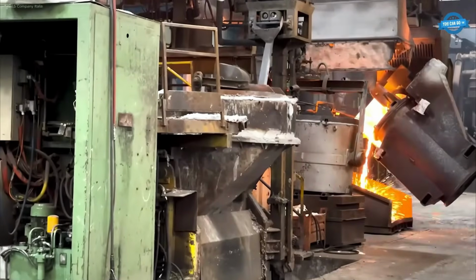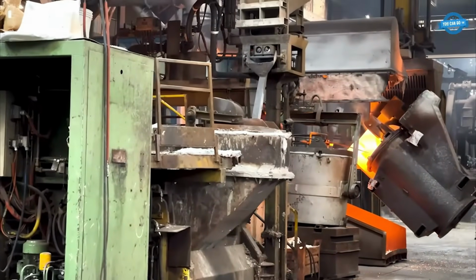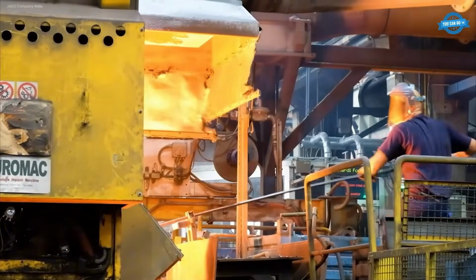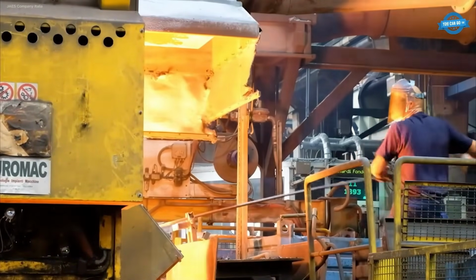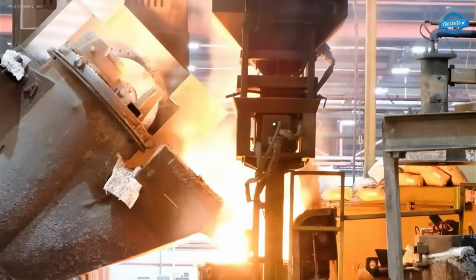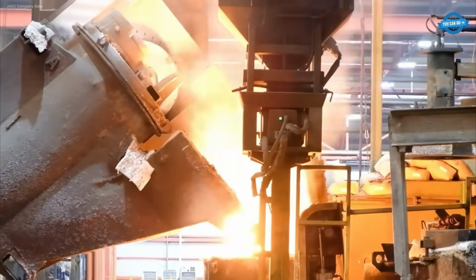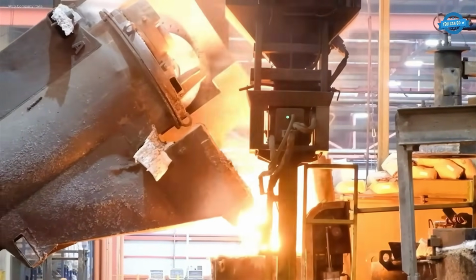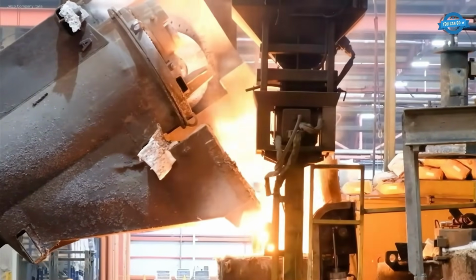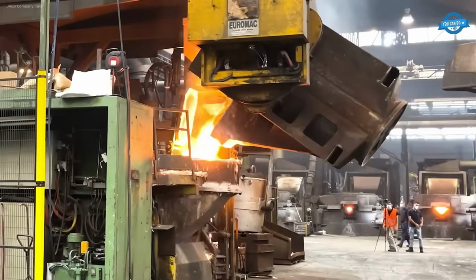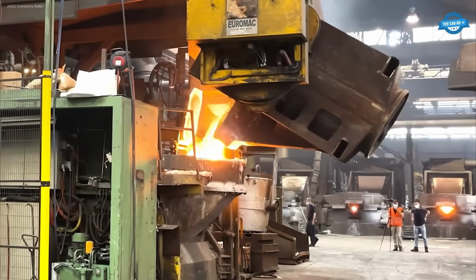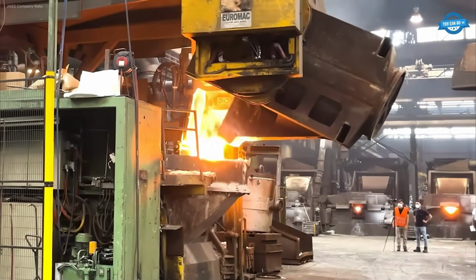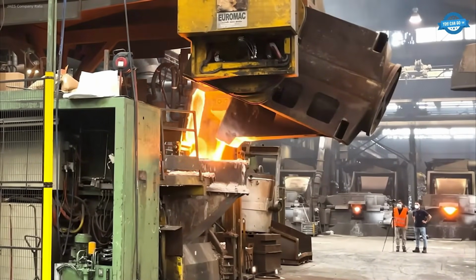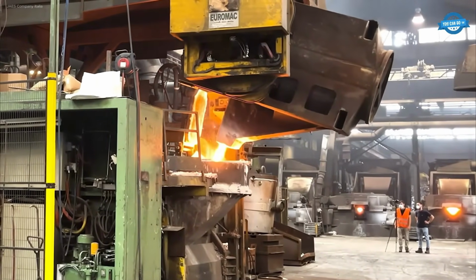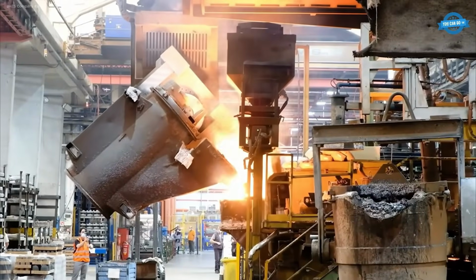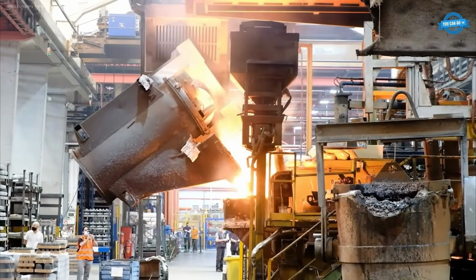Casting is controlled by an automatic pouring system using a sealed ladle, with nitrogen pressurization and a stopper valve to regulate the molten iron flow. Throughout casting, the operator monitors flow rate, temperature, and inoculant dosage via a control system with cameras and PLC software. Quality checks are continuously performed, including thermal analysis and metallographic tests to confirm graphite morphology and spheroidization effectiveness.